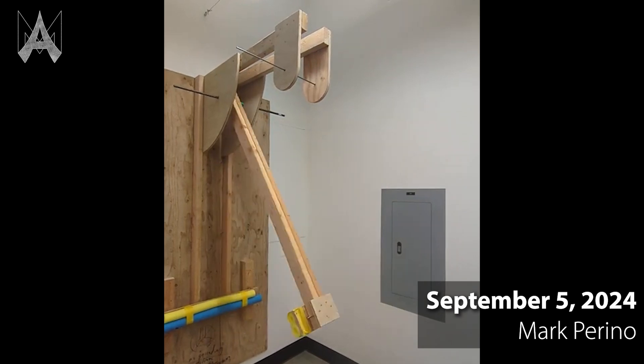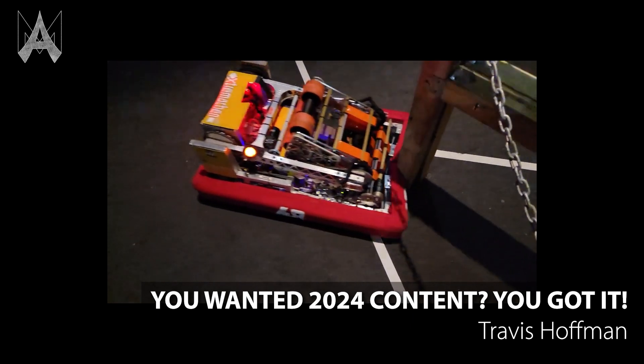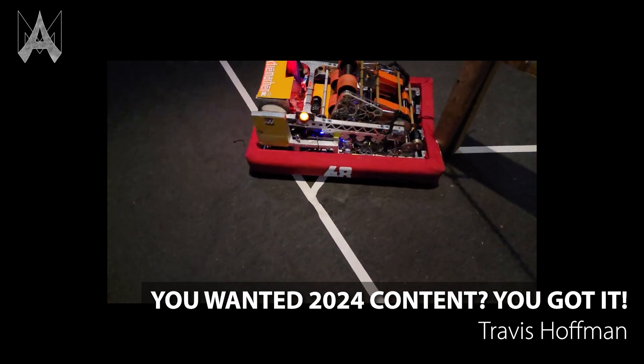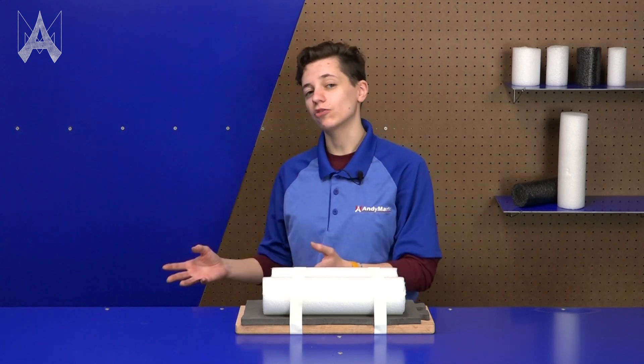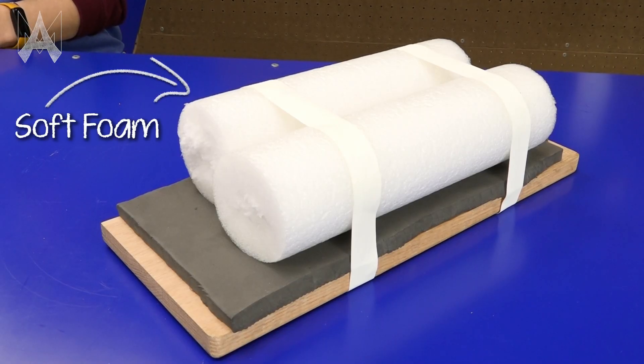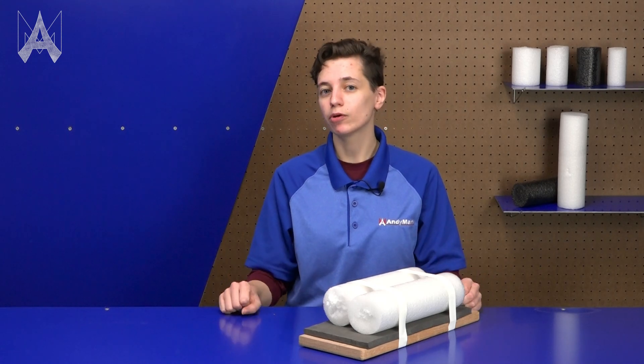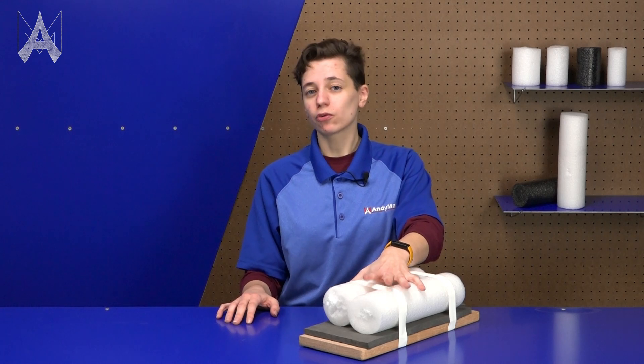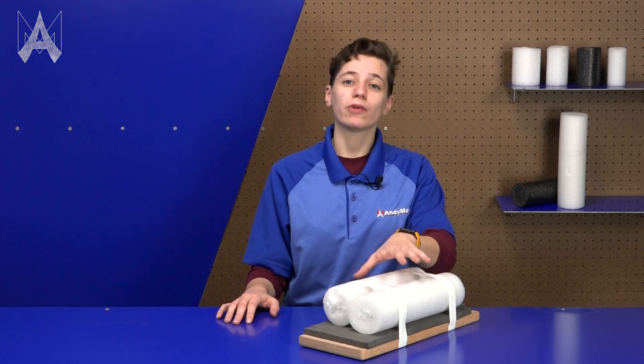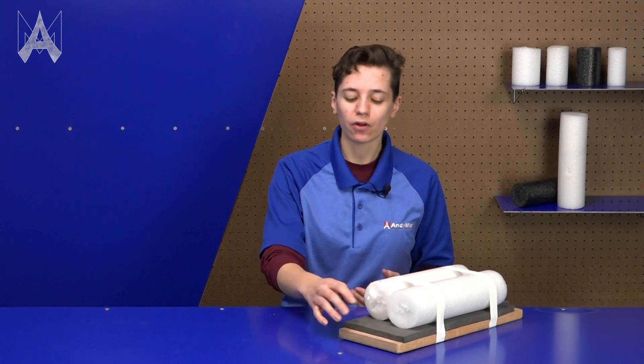These tests included a pendulum test to measure force at small collisions, and also a test where we ran a 115-pound chassis into a truss leg to simulate some of the worst hits a chassis could handle. Based on these tests — both small and large collisions — we opted to use a soft foam and a harder foam in front of a wooden backer. While we don't know if multi-material foams will be legal, we know that any material can be present in the backer. We learned that solid pool noodles, or backer rod, with a density of 2 pounds per cubic foot performed very well, but performed even better with an EVA tile behind them. So we're using the EVA foam as a backer material along with wood to get the performance we want in a legal manner.